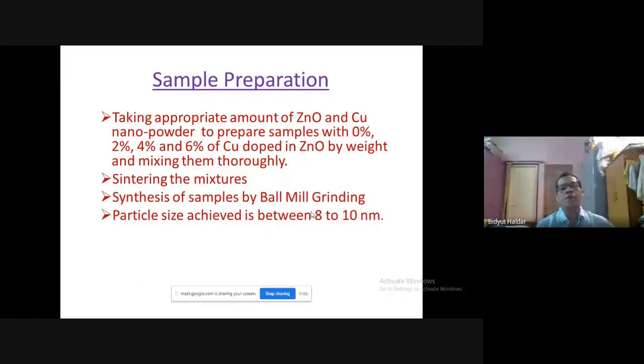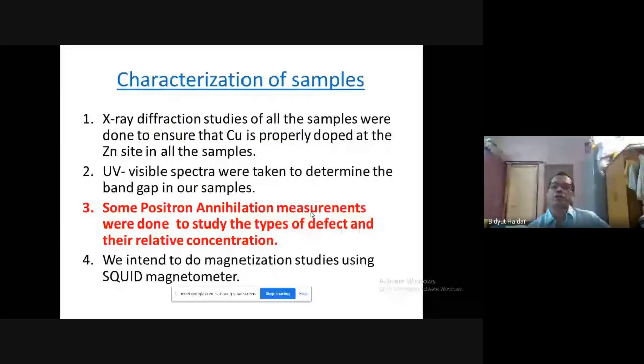Therefore, we made some sample preparations by taking appropriate amounts of zinc oxide and copper nanopowders to prepare samples of 0%, 2%, 4%, 6% copper doped zinc oxide by weight, mixing them thoroughly, sintering them, and then using ball mill grinding. We have achieved a particle size of about 8 to 10 nanometers. And then we are supposed to characterize the samples.